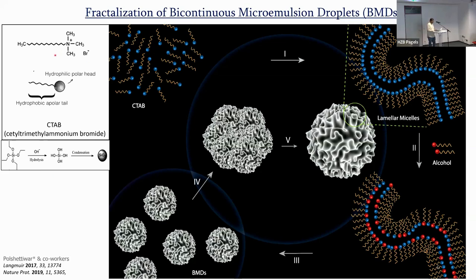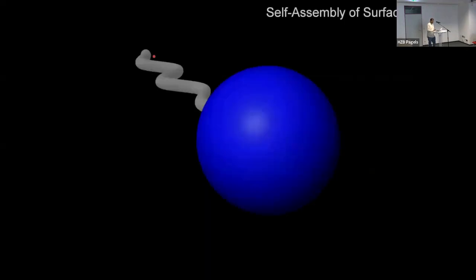So we created a template using this surfactant molecule. Now this is the CTAB molecule. It has this quaternary nitrogen, and that entire group is polar, we call it the polar head, shown as a blue ball in the cartoon. And then you have this CH2CH2 up to 16 times, which is your cetyl, which is a non-polar tail. So whenever you add such a molecule which has a polar head and a non-polar tail, they try to form a surfactant assembly. They try to form micelles. I will show you the animation to understand this better.